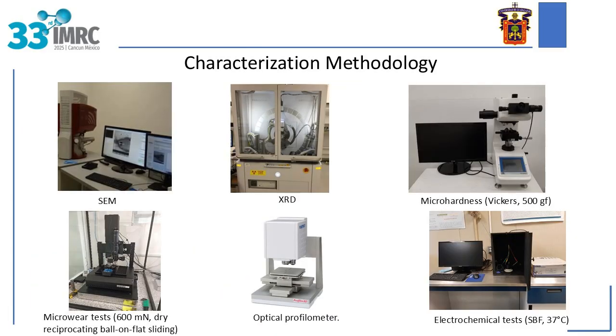The samples were characterized following metallographic preparation, employing silicon carbide sandpaper for roughing and alumina of 3, 1, and 0.05 micrometers, in addition to a 0.02 micrometer silica solution for polishing until a mirror finish was achieved. Initially, the samples were characterized by X-ray diffraction technique, followed by microstructural characterization through scanning electron microscopy images.